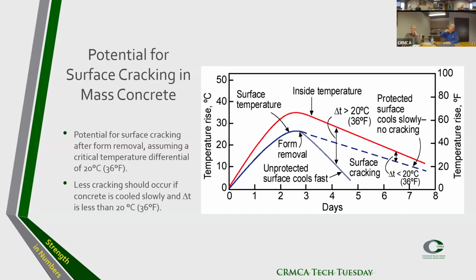This is also from the PCA book. This shows, this is more for mass concrete. Generally, the rule of thumb is that the temperature inside the concrete compared to the surface should not differ more than 20 centigrade or 36 F. So in this example, we see by the heat of hydration how the temperature of the concrete goes up, and then it starts coming down after 2 to 3 days.